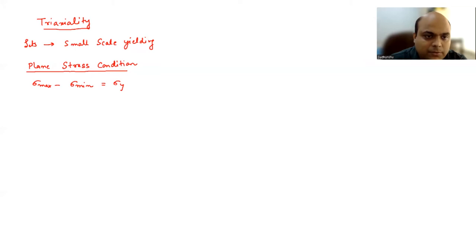your yield strength, okay? Now, when we are talking about the crack plane, remember I mentioned that we will mostly deal with crack plane phenomena. In the crack plane, since there is no shear stress, as I mentioned before, the stresses you are seeing are principal stresses, right? So sigma 11, sigma 22 are principal stresses on the crack plane. So sigma max we can write as sigma 11, and sigma min is sigma 33, equal to sigma y,